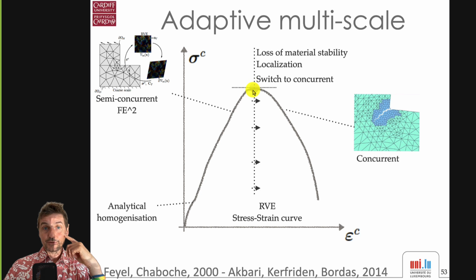When that happens, you lose material stability. You have localization, and therefore you have to switch to concurrent methods. The reason is that if the crack propagated through this representative volume element, splitting it in two, the boundary conditions you used to apply, which are typically periodic, are no longer periodic because you are splitting them using a discontinuity. So you cannot continue the simulation, and you need to switch to a concurrent approach, which is what we did here.